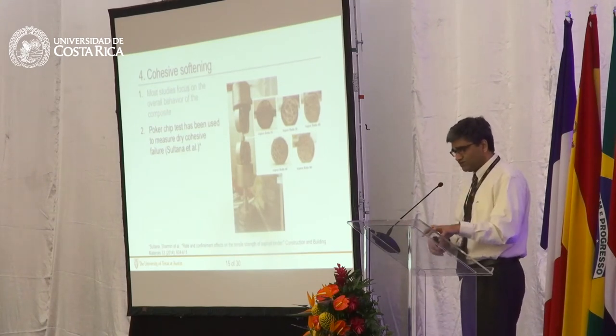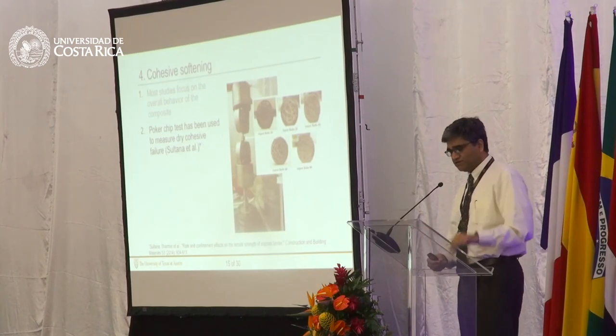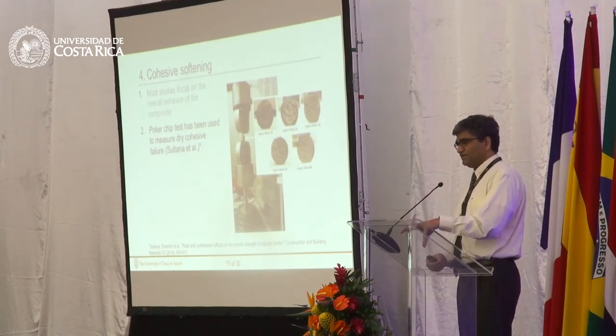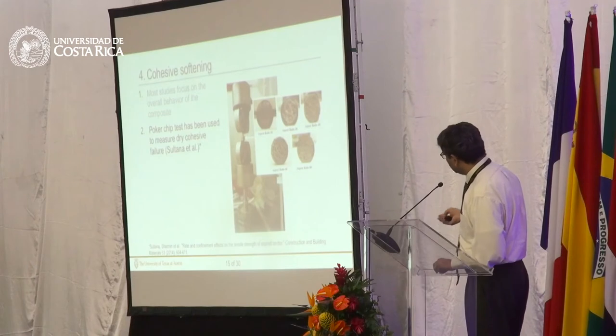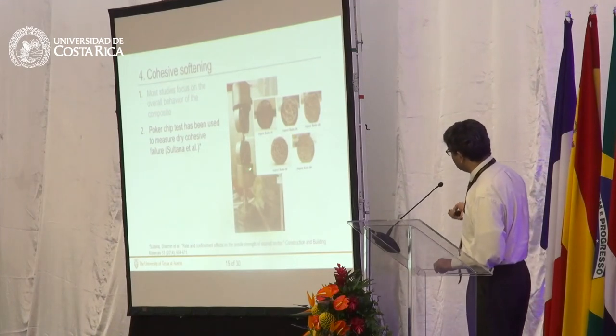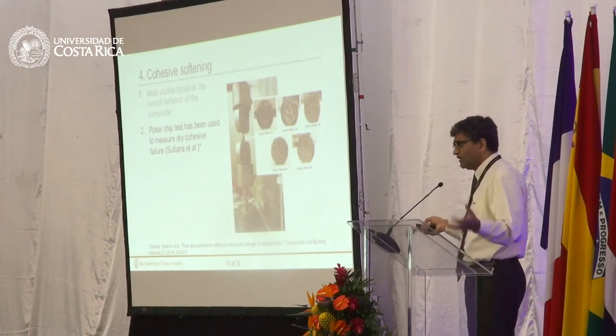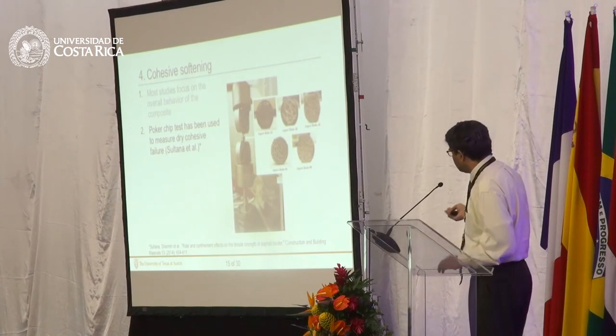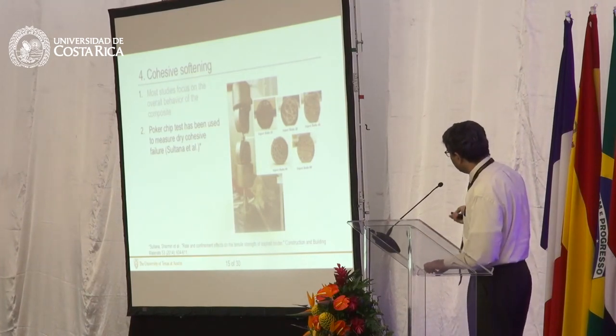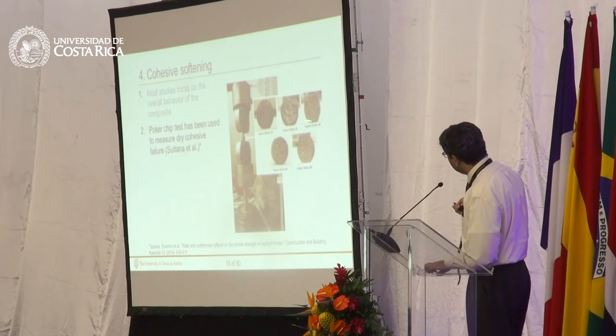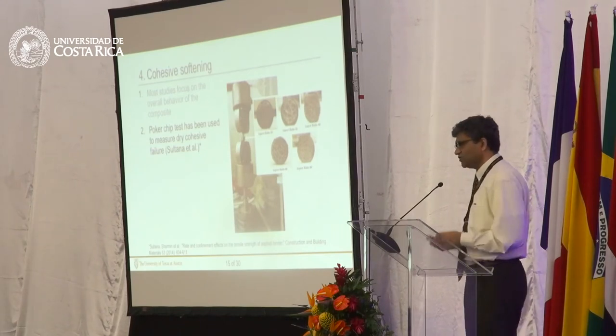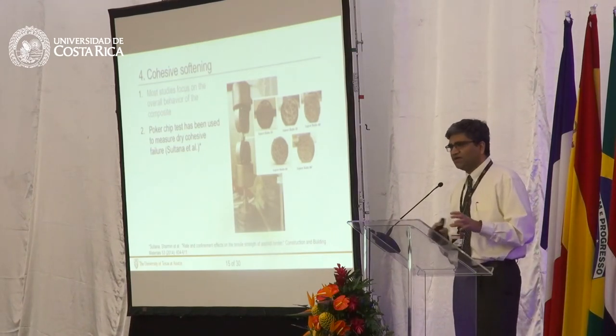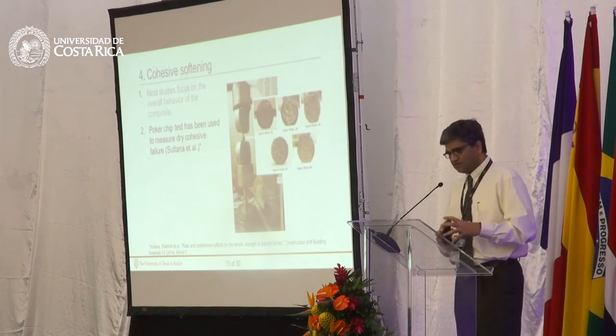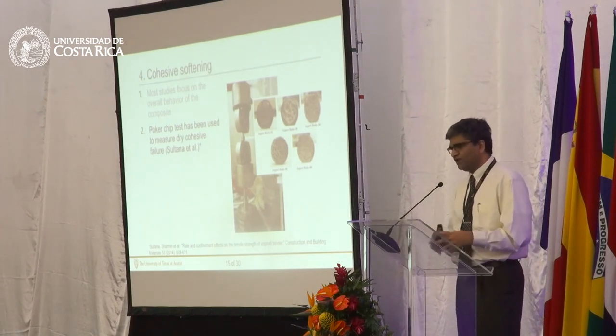Yesterday in the lab tour, I saw that one of the devices sitting there was a PATTI tester, a pneumatic adhesion tester. So although we use a very fancy device to run this test, this is something that you could run off of a very inexpensive device like the PATTI tester, which you already have. And what you see here is cohesive failure, and you see the effect of aspect ratio, and so forth. We've studied this in depth to identify at what point fracture nucleates, at what point you have failure, and so on.